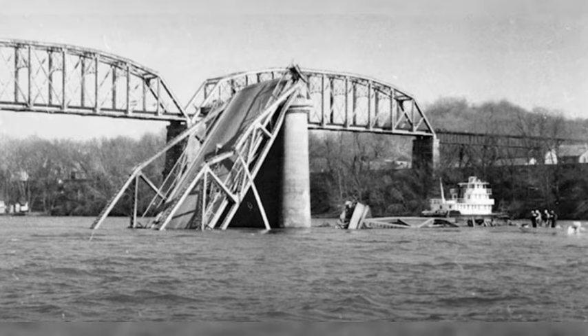Post-war bridge collapses, pressure vessel explosions, and aircraft accidents would repeatedly demonstrate the importance of fracture mechanics. The 1967 collapse of the Silver Bridge in West Virginia, killing 46 people, resulted from brittle fracture of a single eye-bar, exactly the kind of failure mode that Liberty ship investigations had revealed.